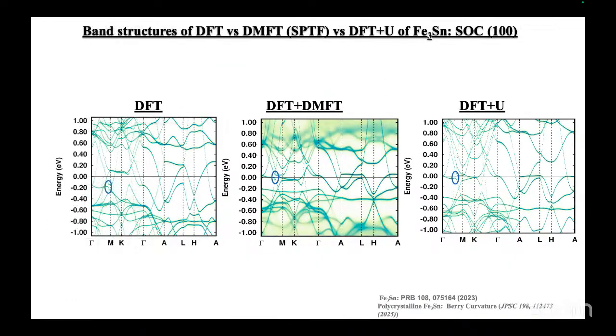Further, looking at how the spin orbit coupling modifies these band features, we did spin orbit coupling calculations, and here we observed similar features to those we saw for the DFT calculation: band opening of the Weyl nodes, and the shifting of the Weyl nodes when we go from DFT to DMFT and DFT plus U.